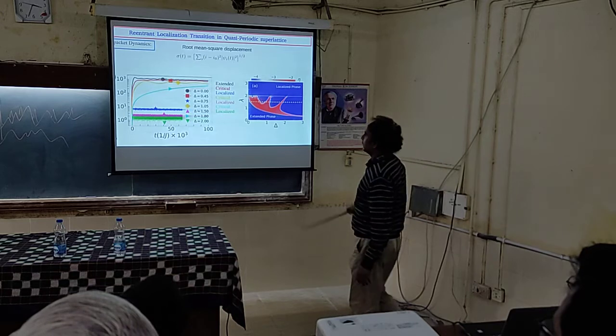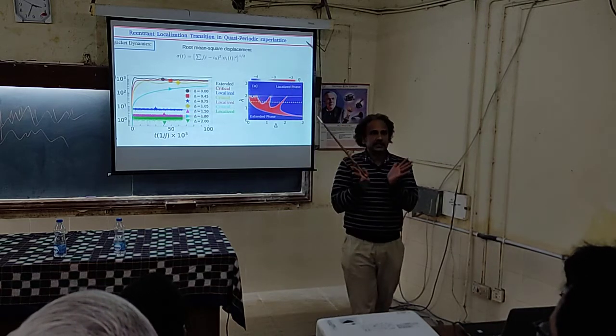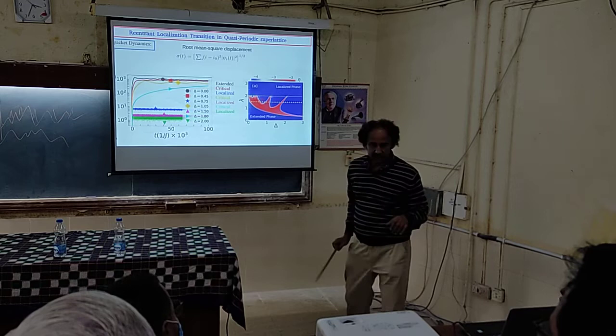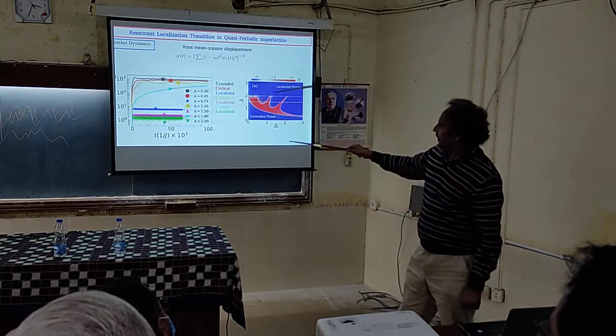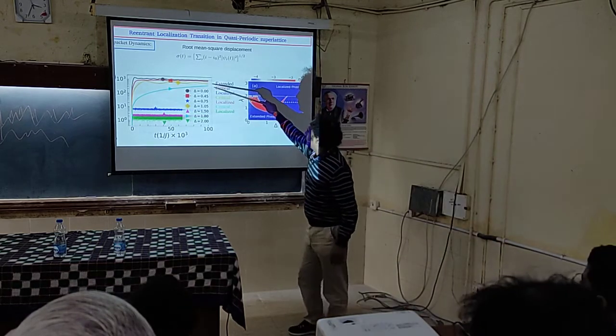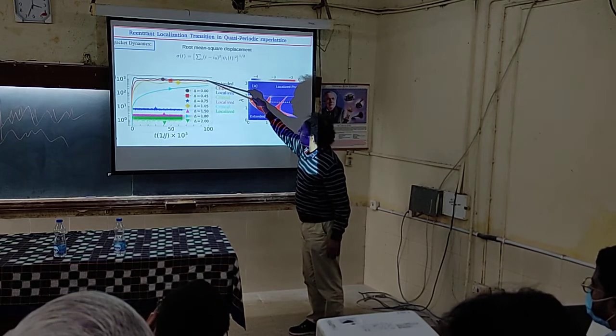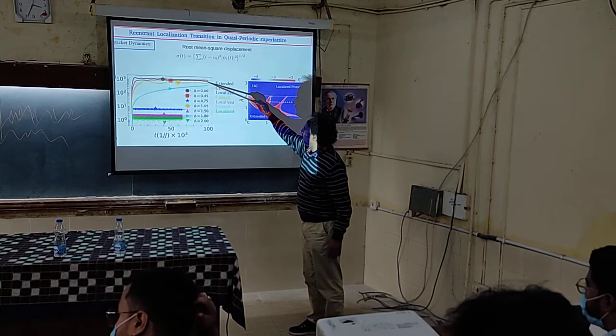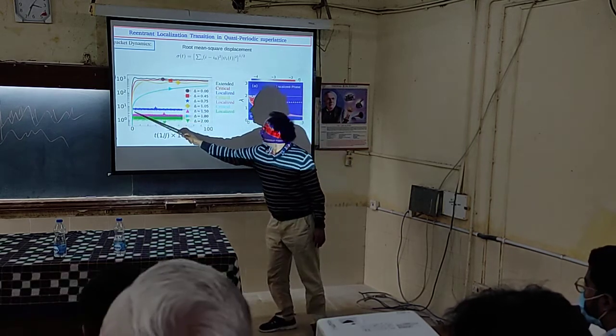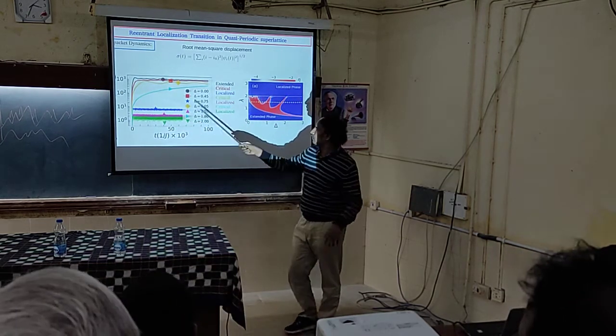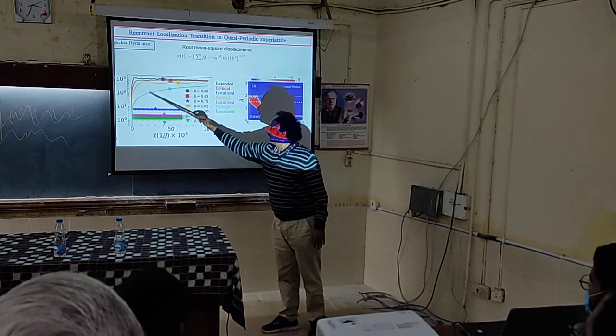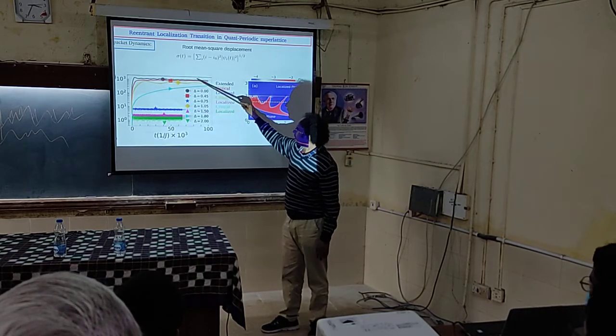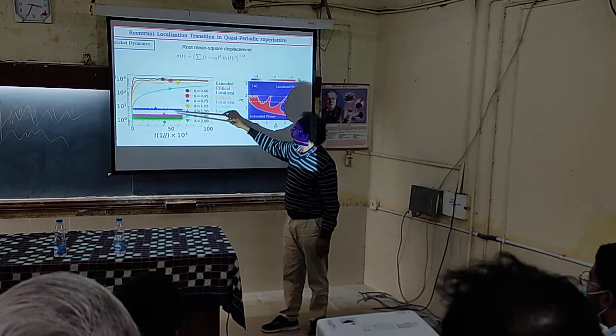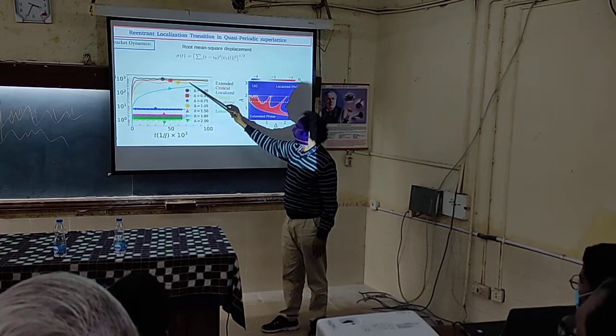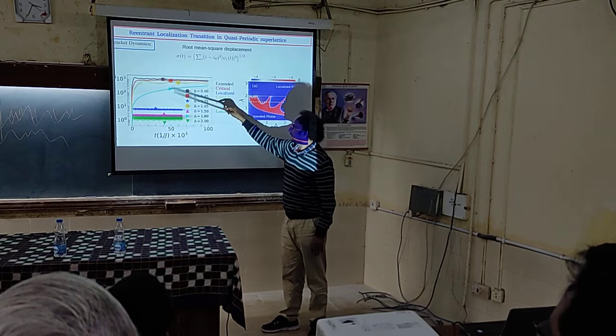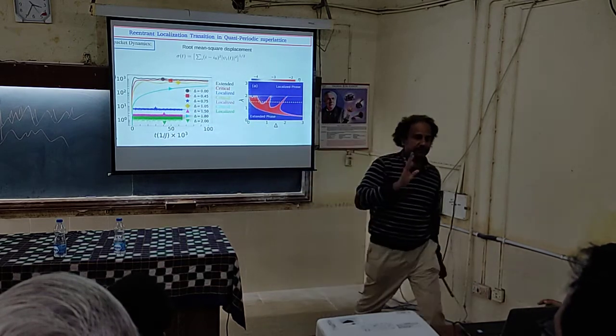What we studied further is the root mean square displacement. What is the displacement of this wave packet? This is sigma t, plotted here. If you look at these profiles, extended, then critical, then localized, because there is no spreading, zero spreading. There is no root mean square spreading. But in the extended and critical phases, there is a finite spreading. So you can see there is a clear re-entrant localization. Black, red, blue, then orange, yellow. So there is a re-entrant feature here.